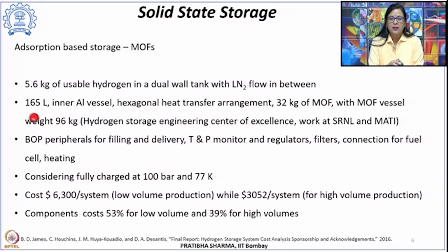So considering a tank of size 165 liters with hexagonal heat transfer arrangement, as reported in the strategic analysis report with studies from the Hydrogen Storage Engineering Centre of Excellence, they incorporated a hexagonal heat transfer arrangement system inside the tank and stored 32 kgs of metal organic framework.